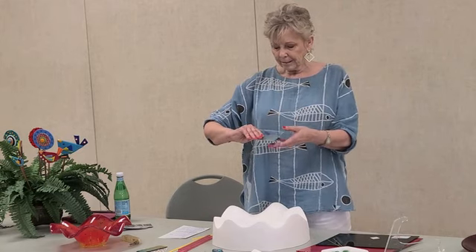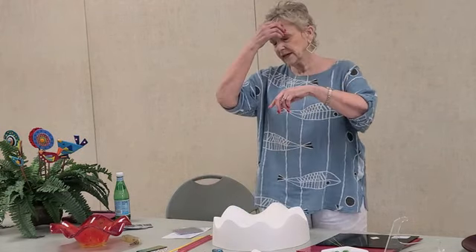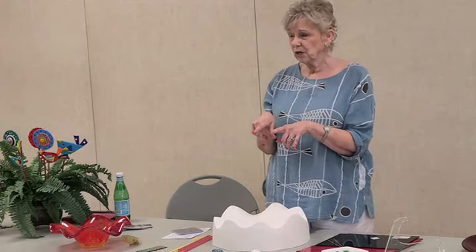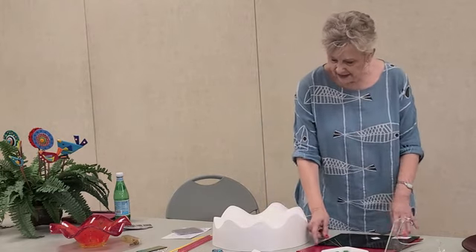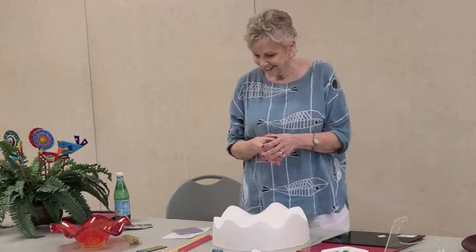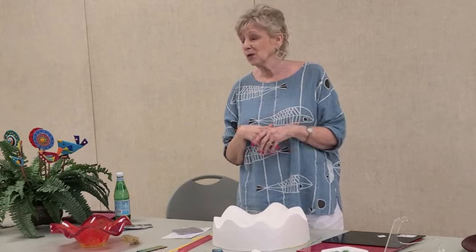And so what I did was I drilled the bubble out. I smoothed it with a grinder, like a Dremel and diamond grinding bits, and I smoothed the hole so it was nice and round. I put it back in the kiln and did something called a fire polish, which we didn't talk about, but it's basically you fuse it just hot enough so the edges of the glass are smoother and not sharp. I had that hole, and one of those little tea light candle holders fit right down in there. It turned out perfect. That bubble was a happy accident, but it forced me to work on it more and not do something new.